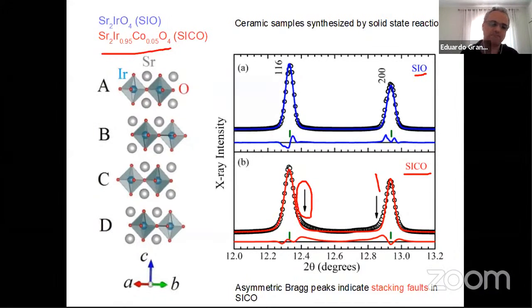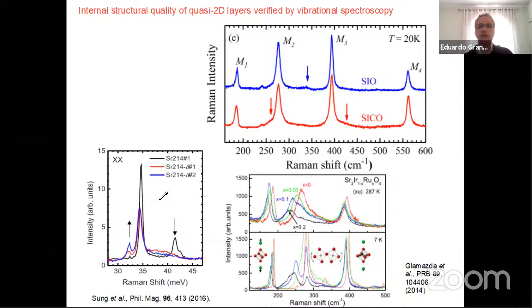That unavoidably leads to some random component in the interatomic harmonic potential, and that's sufficient to disturb this ABCD stacking to something like AB, AB, CD, AB, CD, AB, AB, CD, some variation with respect to the stacking, which has some random component. That's the meaning of stacking faults.